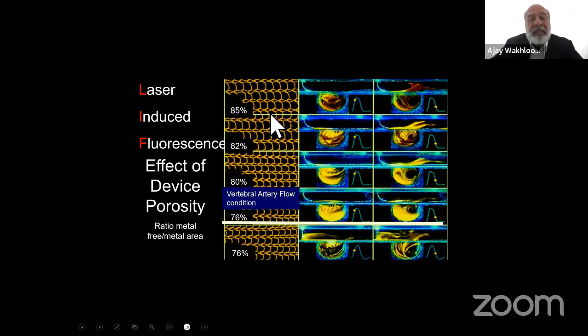What we did then in this model, we started placing the tantalum and the nitinol stents with various porosities. So this is an 85% porous stent, that means 15% metal, and the remaining 85% is free of metal. And what we saw, there was a threshold around 70% metal free, so 30% metal, where there was a flow stagnation achieved over the pulse cycle within the aneurysm pouch.